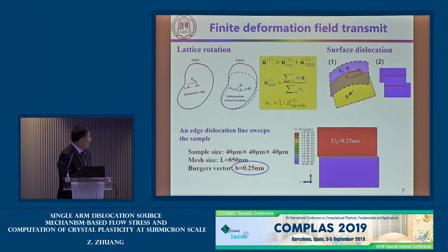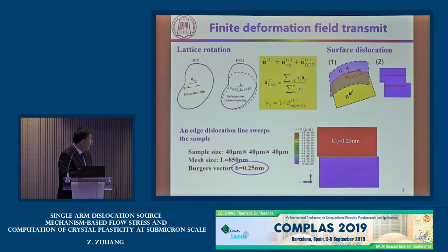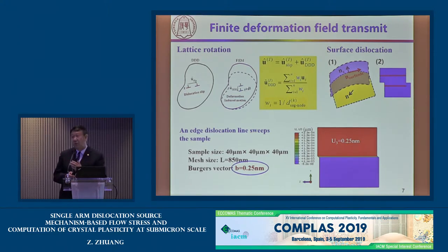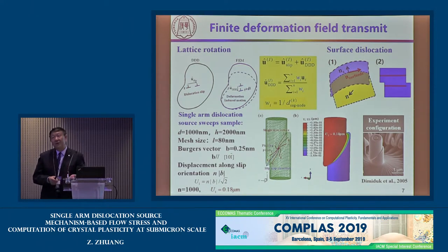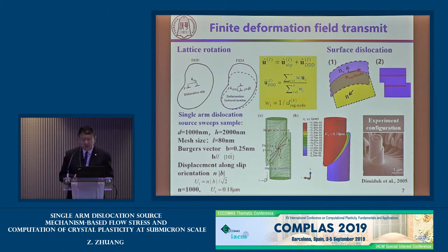For lattice rotation, we give some examples. For these examples with only one slip system, Burgers vectors are very small — only 0.25 nanometers. We can use this DD model to simulate the motion of one Burgers vector. If a pinning point sweeps one cycle, you use one Burgers vector; if it sweeps one thousand times, you accumulate one thousand Burgers vectors, meaning growth from nanometers to microns. From this work, we can compare our simulation to experimental data.